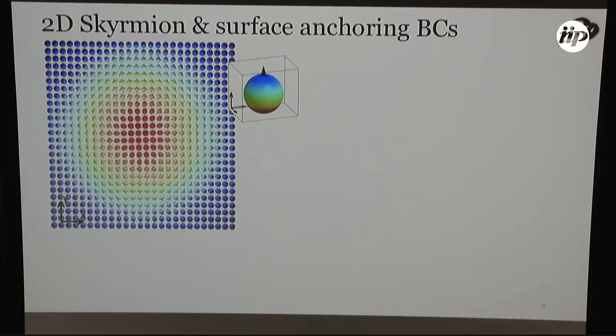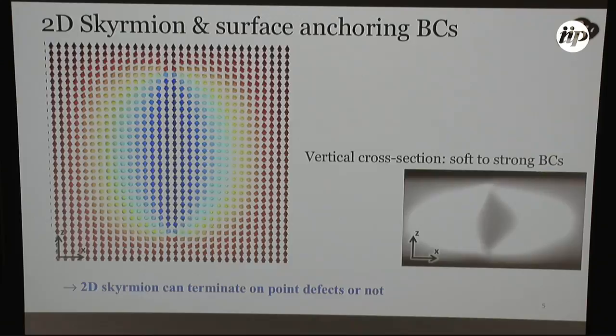And that means that we're looking down onto this structure. So you might start to wonder if this is the same in 3D space or if there is some kind of variation as we look three-dimensionally at our structure. And the answer to that lies in the boundary conditions. So here you can see, as we look from the side here and here in our numerical simulation, that we have a localized structure in three dimensions that is stabilized near the substrates by hyperbolic point defects.